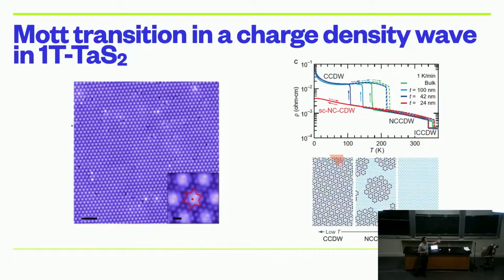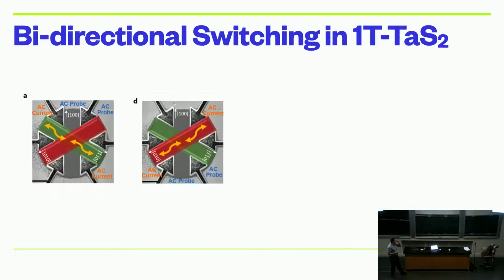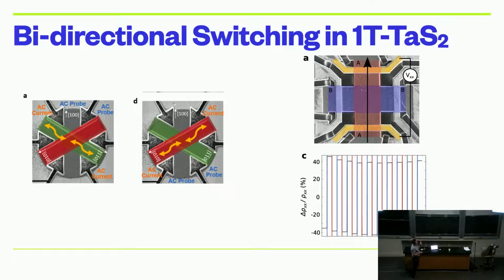Well, here's the data for that. It's kind of neat, because what it's telling you is that just by the cooling rate that you use for the system, you can go from an insulator to a metallic transition. So I really thought this might be another system on the border of a metal insulator transition. Okay. We were seeing some super weird signal. We made all these devices. Finally, once we landed on the right geometry, you can have the same kind of effect of blue pulse, red pulse, high resistance, low resistance. It turns out that because it's on the border of a metal insulator transition, it's orders of magnitude larger signal than what we were seeing in the previous systems.